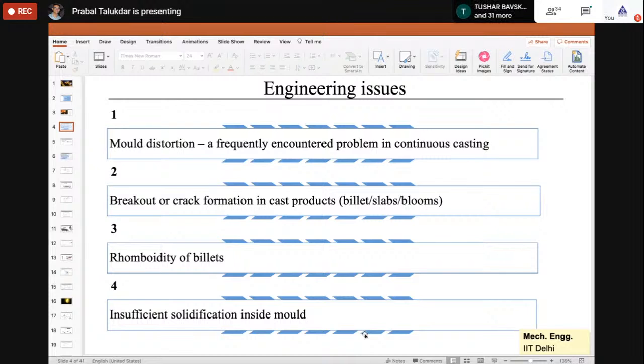If distortion of the mold takes place, that means its shape is changing, so all your calculations don't work. You have a certain taper in mind at the beginning of the design of the mold, but later its shape has changed, so whatever steel product you get from this mold could be different. So mold distortion is one phenomenon which is important to study: what is the amount of shrinkage, or the amount of deformation you get in a mold. If there is more distortion in the mold, then maybe you have to increase the cooling liquid, so that you can still keep the temperature of the mold at a lower level. Maybe the casting speed also has to be changed, so that the mold can last for a longer time. Those kinds of remedies can be taken.